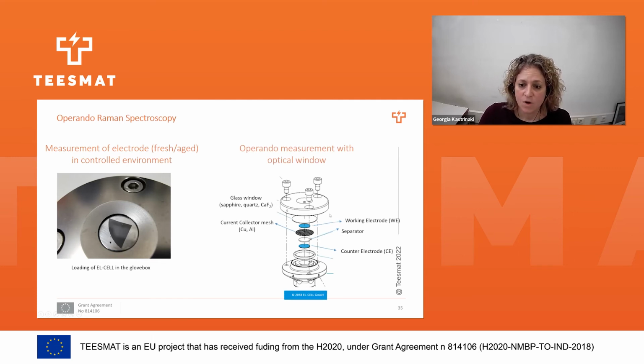And typically this is how we synthesize inside this cell, for example, a lithium ion cell. So we have our counter electrode at the bottom, so we cannot have optical access to this according to this structure. Then we put on the separator. Then on top we put a mesh. It can be copper or aluminum. It depends on what the electrode on top is, if it's a cathode or an anode. And then we put on our working electrode, which is deposited again on copper or aluminum foil.